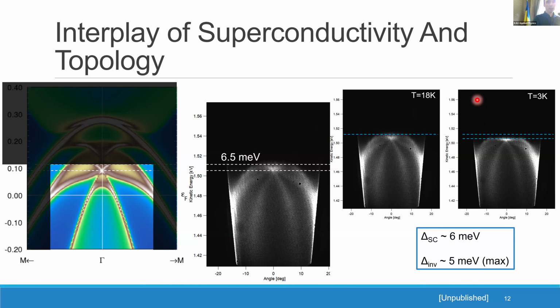And it showed us that this Dirac point, which should be where the surface states arise, is just slightly lower than the superconducting gap itself. This is the non-superconducting state, and this is the superconducting state, because again, Tc for it is around 18 Kelvin. That means that if we have an inverted gap of that size and the superconducting gap is so big, it bends it farther away from the Fermi level, and it also squishes it.